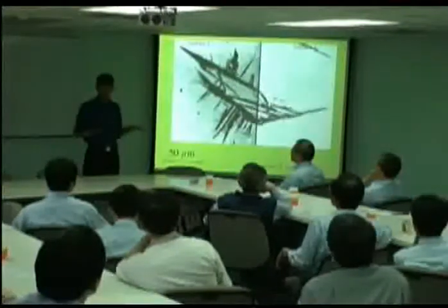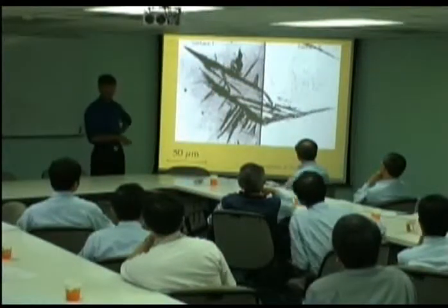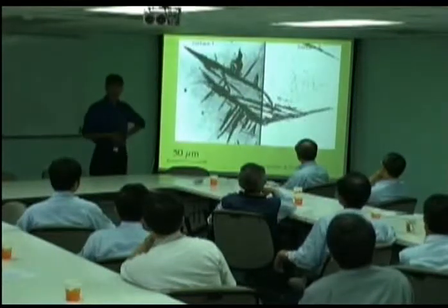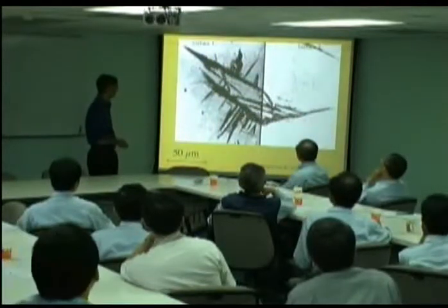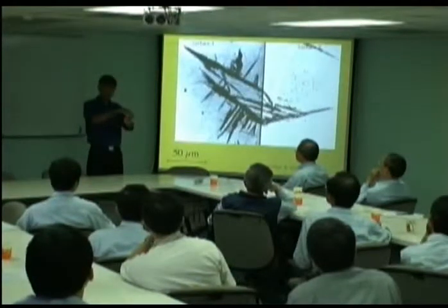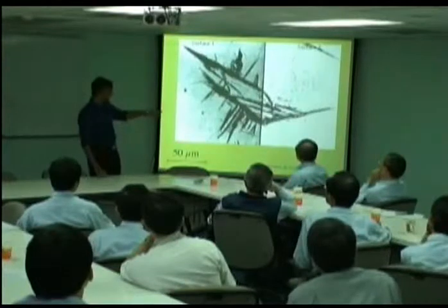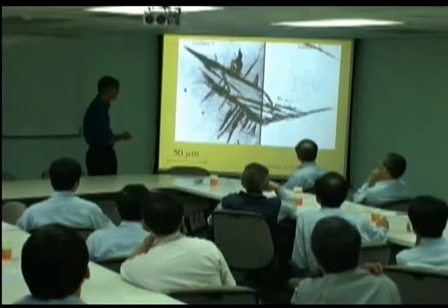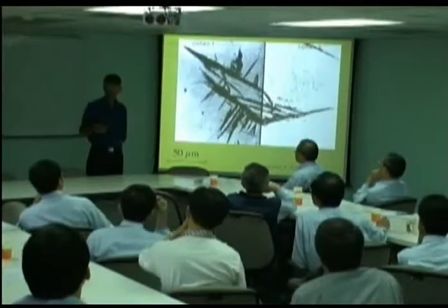Now, the second thing that we need to understand is that bainite is always in the form of a plate. This is a very, very nice micrograph taken by Srinivasan and Wayman in 1968. And this is a technique that we seem to have forgotten. Here we are looking at two different surfaces. We're looking at a specimen which is shaped like that, so we can follow what happens to a face across the edge here. And we get a three-dimensional image of the bainite. And you can see that in three dimensions, it is a plate shape.